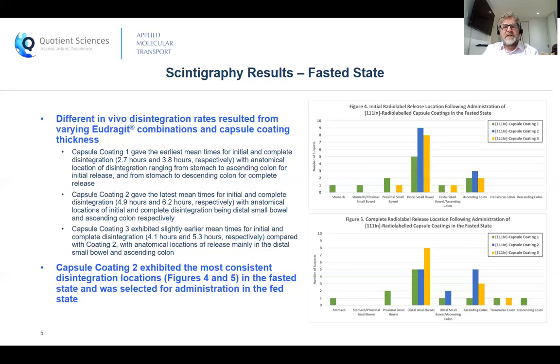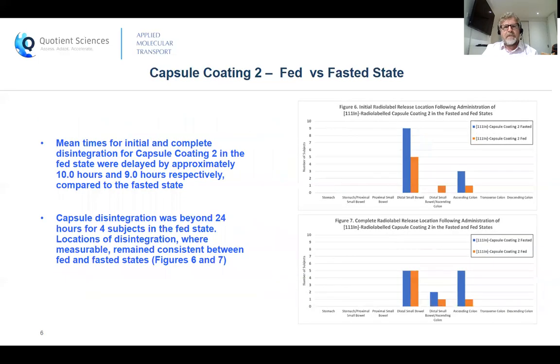Following a review of this scintigraphy data from the fasted dosing, it was decided to select capsule coating 2 to administer again in the fed state. On slide 6, we have similar bar charts in figures 6 and 7, showing the same fasted data for capsule coating 2 in blue, but this time with the fed data for the coating system now added in orange for comparison. In the fed state, as could be anticipated, the mean initial and complete disintegration times were delayed by around 10 and 9 hours respectively.